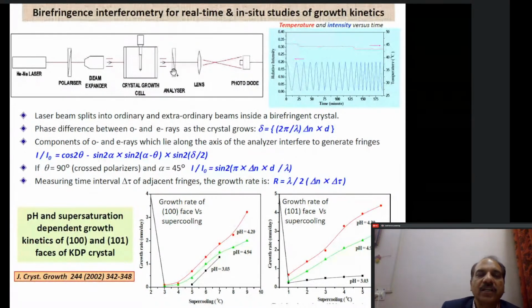And then these extraordinary and ordinary rays pass through an analyzer. Initially we align the setup in such a way that the polarizer and analyzer are crossed to each other. So at the output, we will not see any output beam, right? Now you put the crystal inside the growth chamber. Because the crystal is birefringent in nature, the plane of polarization of the incident light will change, and then some of the light will be able to pass through the analyzer, and the component of the E and O, which is along the axis of the analyzer, will interfere, and it will produce an interference pattern. And this interference pattern will continue to change as the crystal grows, and depending upon how many fringes have passed the field of view, you can find out the growth rate of that crystal along that direction.